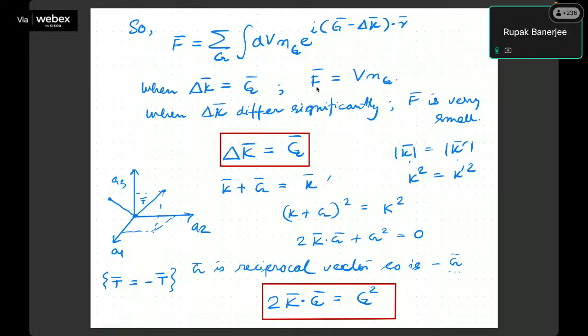But when is this happening? When is this maximum? Only when delta k equal to G. If delta k varies significantly, if delta k and G are not matching, then this will basically die out, it will oscillate out, which means it will give you almost no or zero peak or noise level peak. So F, the scattering amplitude, could be very small or considerable and substantial, depending upon whether delta k is equal to G or not.